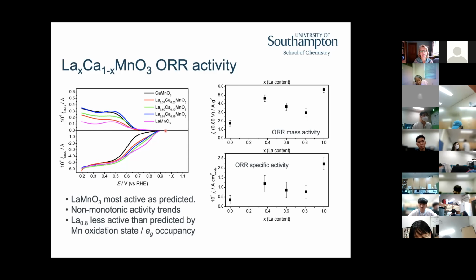So that's that mechanism. With the lanthanum manganate, it's really interesting. We get onset at much more positive potentials, and only when we get to these potentials do we start to see the peroxide. So there's a slightly different mechanism going on in this region than that region. Okay. And we looked at the effect of changing the content on the mass activity and the specific activity. So we don't get monotonic trends, and this lanthanum 0.8 is really less active than we would have predicted from the EG occupancy.